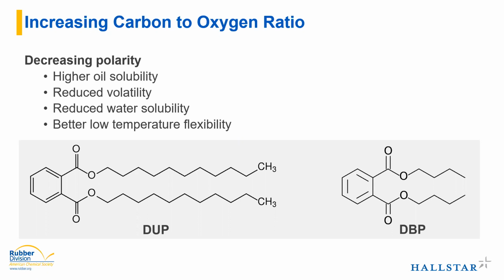Converse to the higher oil solubility, you see reduced water solubility. Water is very polar, so as you decrease polarity, your ester will be less soluble in water. And then you usually see better low temperature flexibility as you decrease your polarity as well.